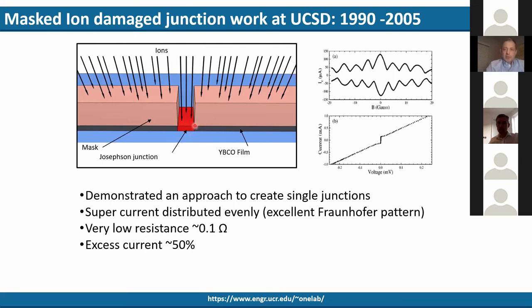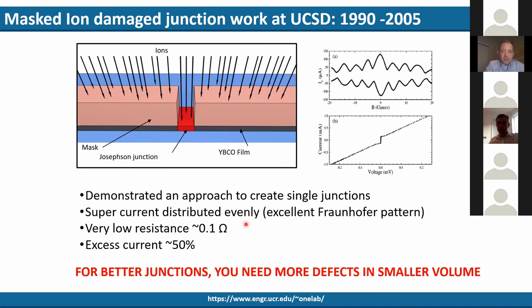So in practice, what folks would do is they just would damage this down so that the TC would just reduce by maybe 10 Kelvin. So if you have a 90 K superconductor, you beat this TC down to around 80 Kelvin or so, and you run the device at 77 and you get a proximity effect junction. And here's some data from some of those early proximity effect junctions. And they had really well distributed current because they show that Fraunhofer pattern, but the resistance is quite low. And when you have these really low resistances, these Josephson junctions, it picks up every bit of environmental noise and they're actually really hard to work with. And also your ICRN product is really small. And you have excess current, which I think many of you probably are familiar with because I've heard you talking about Blonder, Tinkham and Klapwijk. And it's just a natural thing that comes out of an SNS type junction.